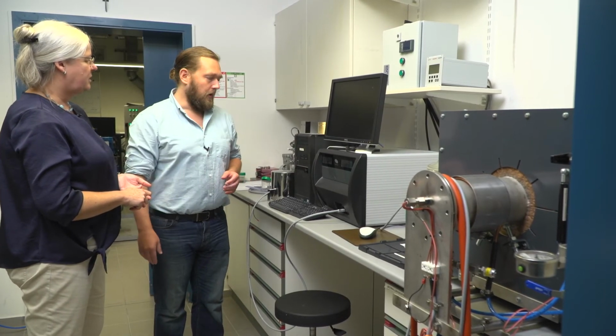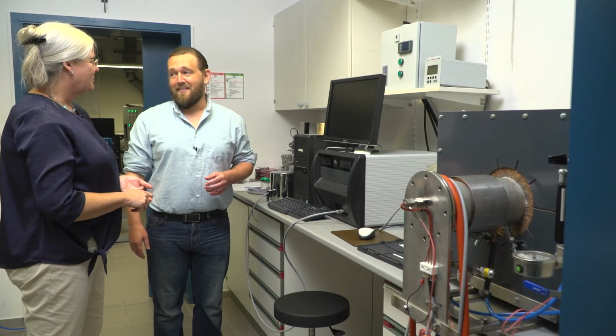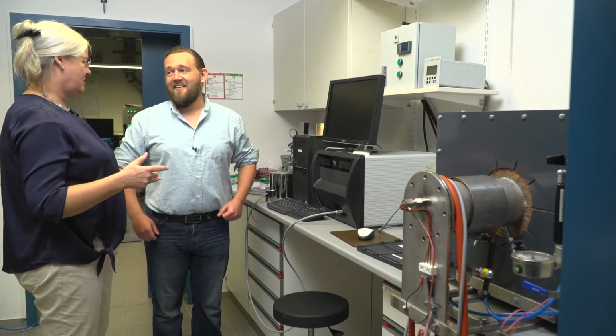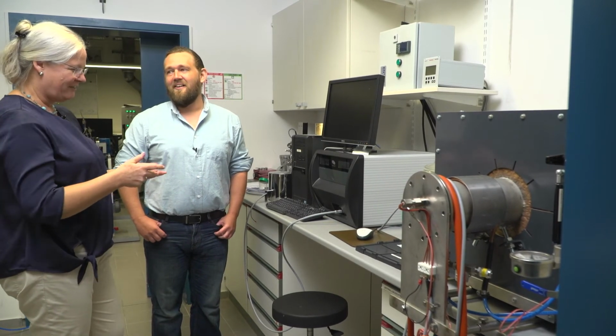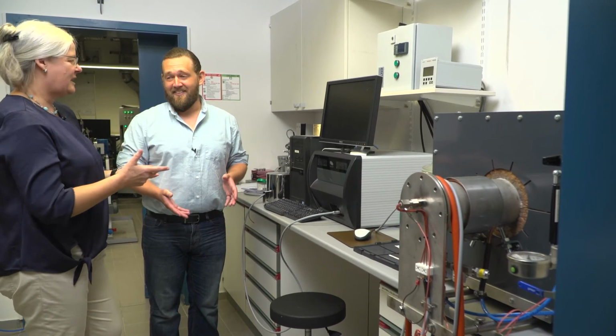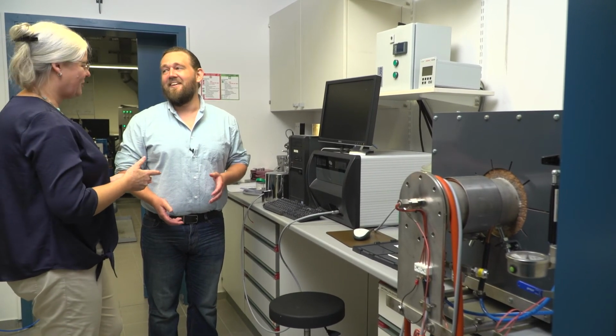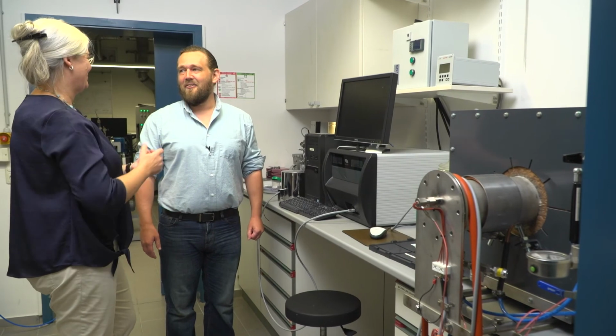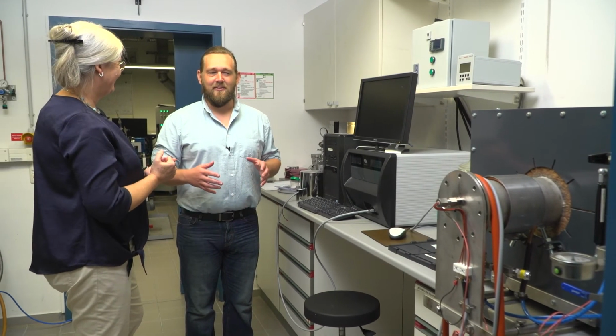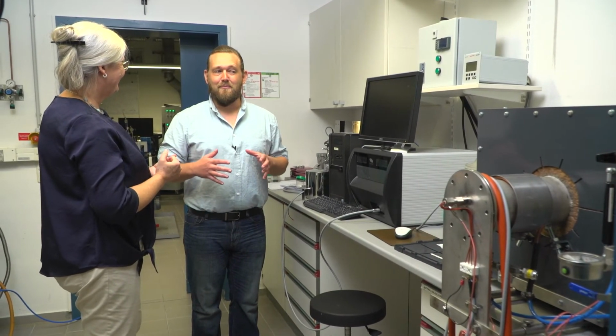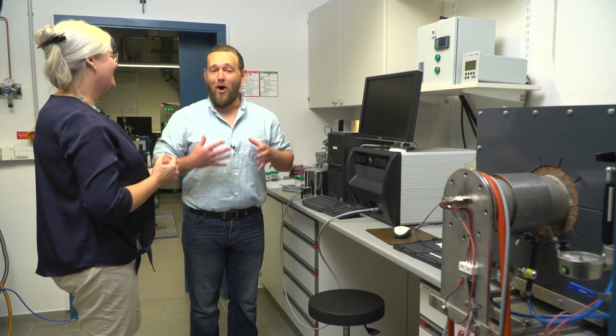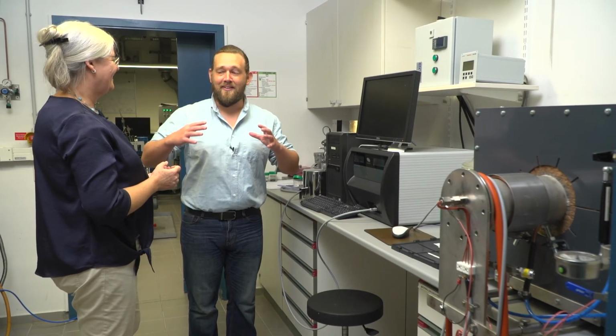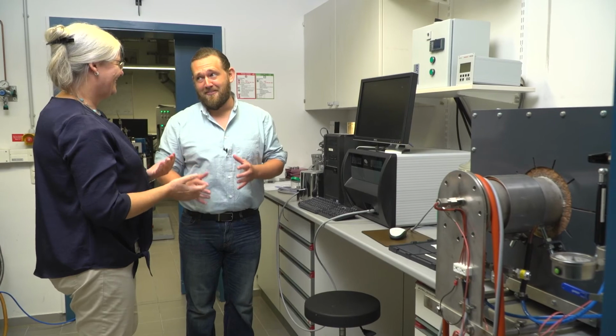Yes, but it's not easy with aerogels. Because they don't see the temperature, and therefore you measure nothing. So actually, you always have the same value as at room temperature, because you do not reach the temperature. So not only are they really good insulators, but they're really difficult to measure how good of an insulator they are because they don't let heat into them. So it's kind of a paradox. A little bit, yes.